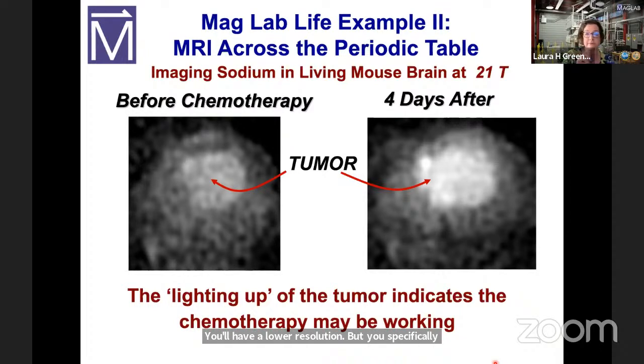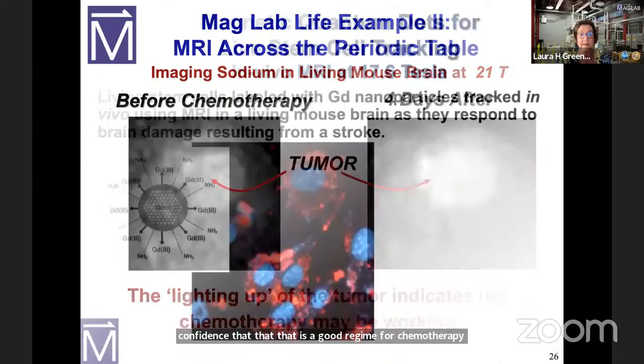Why would you want to detect sodium? Well, when cells are dying, they uptake sodium. The actual mechanism isn't completely understood, but we know that happens. So this is what you do. You image the mouse's brain on the left side in the sodium, and we see where the tumor is. You give the mouse chemotherapy and measure it 4 days later. You can repeat that. And if that sodium lights up, like we see on the right here, that says that area has been uptaking sodium. The concentration of sodium is higher, indicating that those cells are probably dying. And that gives you some confidence that that is a good regime for chemotherapy. So this could be really life-changing for many, many people.